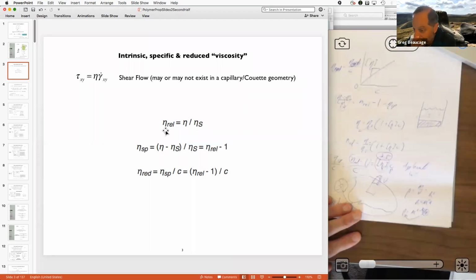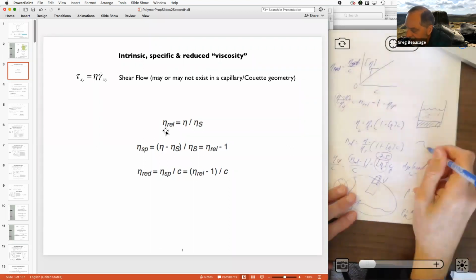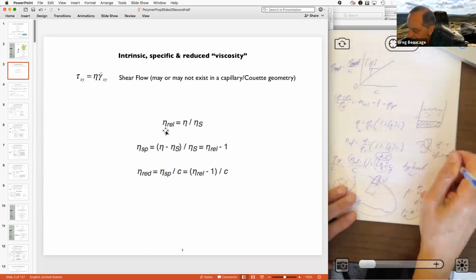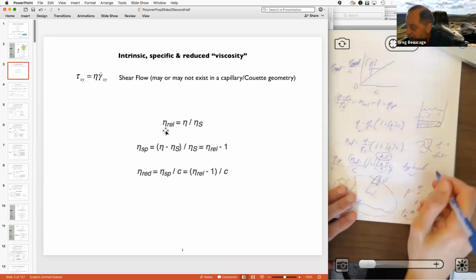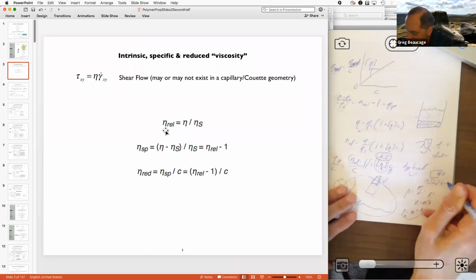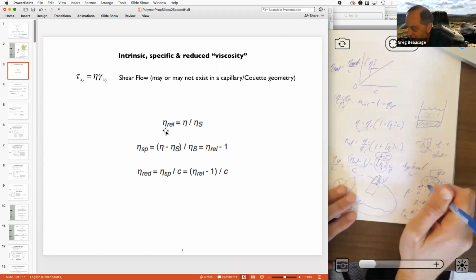All right, so people will make correlations with fractal dimension. If you have a linear chain in a theta solvent, it's got a fractal dimension of 2. And if you branch that chain randomly, it's got a fractal dimension of 2.5. Or we saw that if we took a sheet of graphene and let it form a self-avoiding walk so it crumples, it goes from a dimension df of 2 to a dimension df of also 2.5. So you can see that a crumpled graphene sheet and a randomly branched polymer aren't the same thing, right? But they have the same fractal dimension.